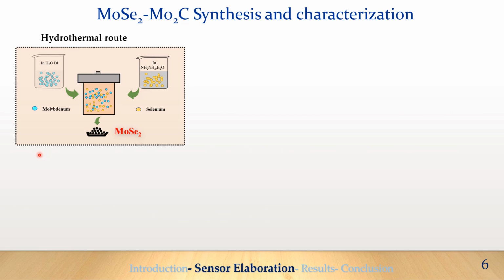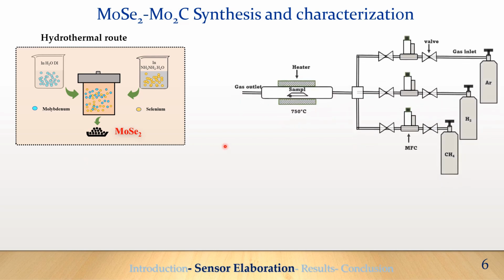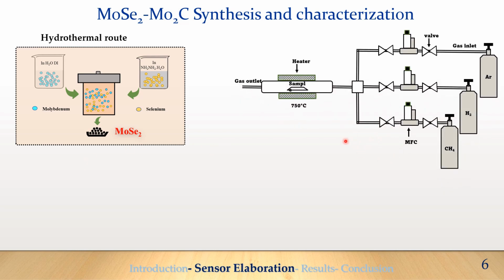So for the sensor elaboration part, MoSe2-Mo2C was synthesized by hydrothermal method using hydrazine as a reducing agent and molybdenum and selenium as starting materials. Then, the powder obtained was heated at 750 degrees Celsius with a mixture of argon, hydrogen, and methane at optimal conditions to obtain MoSe2-Mo2C.